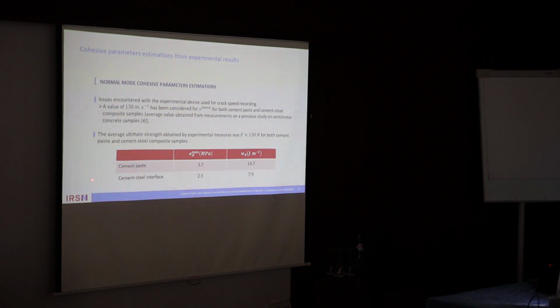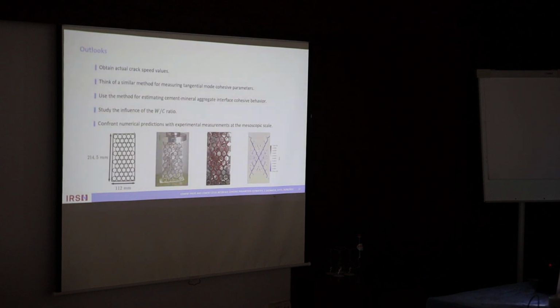So at last, here are the normal mode cohesive parameters I have estimated for the cement paste bulk and the interface between cement and steel. These results may be improved by measuring actual crack speed values. We could think of a similar method also for measuring the tangential mode cohesive parameters.